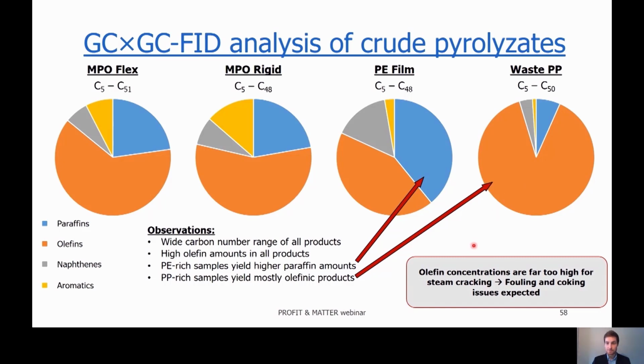Concluding, it can be said that the olefin concentrations of all 4 samples are still far too high for steam cracking. This would mean that we expect a lot of fouling and coking issues in a steam cracker when cracking these fractions crude without further treatment.